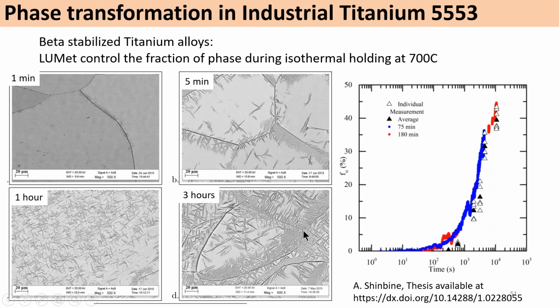The longer we wait, the more the fraction of this alpha phase will be in the sample. And as the velocity in this alpha phase is different than the velocity in the beta phase, we can actually measure the fraction of alpha growing in the sample during the time using the velocity obtained by the Lumet measurement. And of course, as we have done in all the studies, we've validated our measurement using metallography. That is to say, by analyzing the phase fraction in this sample.